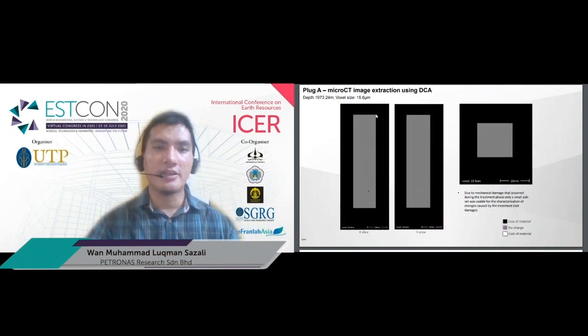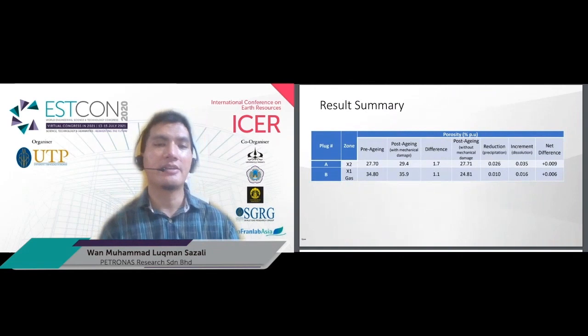As you can see here, with the help of DCA, we managed to extract a subset for our porosity changes study. Here, we were able to determine the porosity changes due to dissolution, represented by the black dots, as well as porosity changes due to precipitation, represented by these white dots. And here is the result summary for plug A and plug B, which are the plugs taken from X2 and X1 gas. For comparison purposes, we are showing porosity changes both with and without mechanical damage.